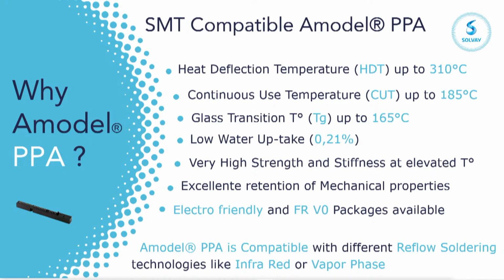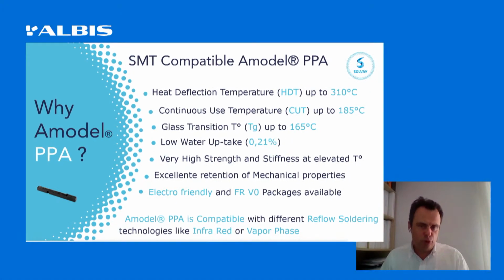In addition, PPA offers low water uptake, around 0.2%, high strength and stiffness even at temperature, and an excellent retention of mechanical properties. The material is available with an electro-friendly package, to avoid electrocorrosion, and if needed, with a flame retardant package. So Amodel PPA is clearly compatible with different reflow soldering technologies, like infrared or vapor phase.